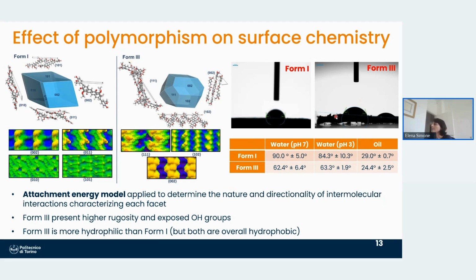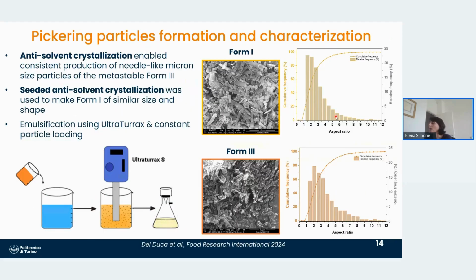So it's still not hydrophilic enough to stabilize oil in water. So we could only work with the water in oil emulsions, but still we could see some differences when making these emulsions. So the first thing that we needed to do was to find a procedure to make these particles at micron size, which is suitable for food formulation.